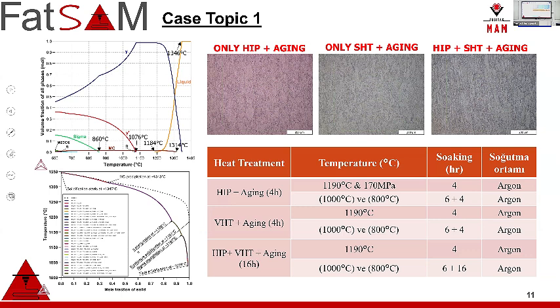As we know, the physical properties of any metallic materials can change or are a function of either temperature or pressure. So in this case, we apply both. If you increase the pressure, the transformation temperatures will decrease. This is a big advantage. You will have much more dense microstructure because of the pressure. You have ordered structure depending on the isostatic pressure and applied heat. And you don't necessarily need to reach certain temperatures because of the pressure. So it's very advantageous. But does it work? It's a question mark.